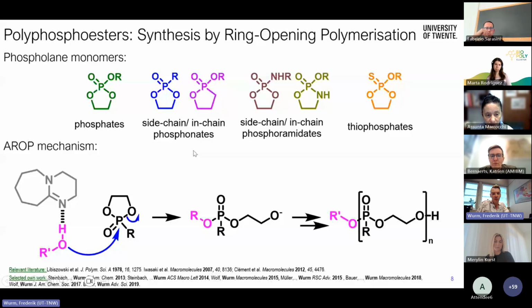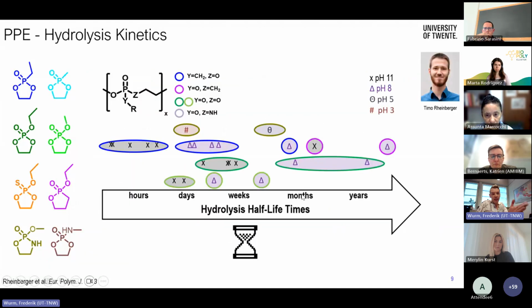The synthesis from the chemical point of view is a normal ring opening polymerization. We use normally metal-free catalysts, alcohol as an initiator, and then this would be the homopolymerization. But at the same time, you can also mix lactones in. And that is what our PhD student Sanchi started, screening different of these phospholane monomers.